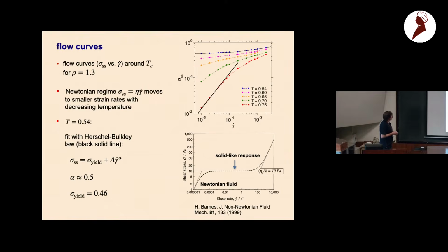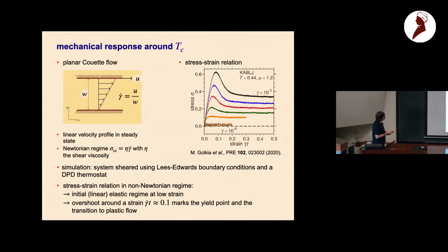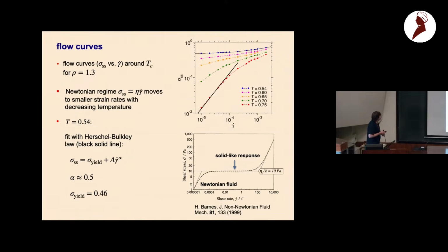Okay, so here are flow curves. We can read off the steady state stress at very large strains and plot it as a function of the strain rate. This is now for density 1.3, different examples. TC is here at 0.65. This is a very low temperature at 0.54, and here 0.75. At 0.75, we have access to the Newtonian regime, so we have a linear relationship between the steady state stress and the shear rate.